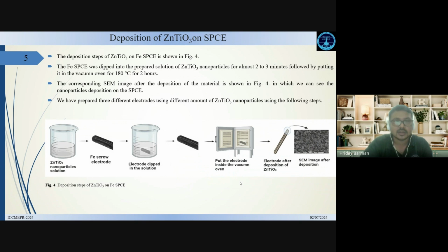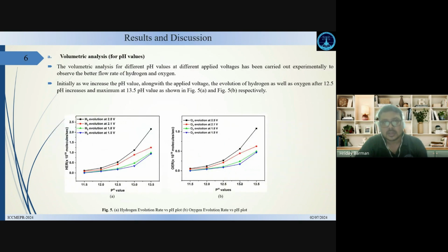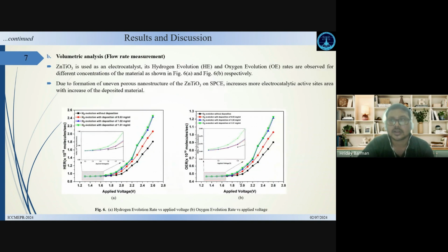Before going to the flow rate measurement, we have done the volumetric analysis for different pH values, to see at which pH values we are getting the highest flow rate. For that we have done this for 4 different applied voltages at different pH values. We are getting the highest hydrogen and oxygen evolution rate at higher pH values and higher applied voltages.